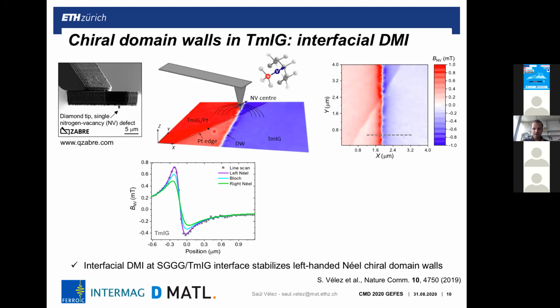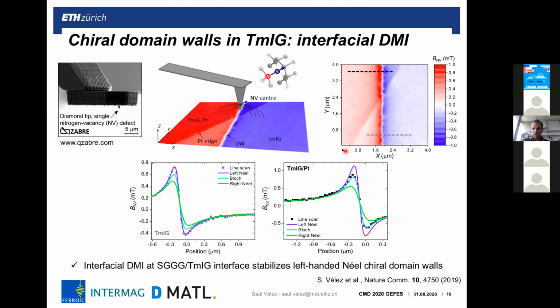In the part where we only have thulium iron garnet with no platinum on top, we observe that the domain walls are left-handed Néel. And when we have platinum on top, we partially quench this chirality because of the positive DMI. So in conclusion, with these measurements, we observe that we must have a Dzyaloshinskii-Moriya interaction at the interface between the thulium iron garnet and the substituted gallium garnet substrate. And on top of that, we also have a Dzyaloshinskii-Moriya interaction from the platinum layer on top, which partially quenches this DMI because the contribution of that interface opposes the one of the substrate.